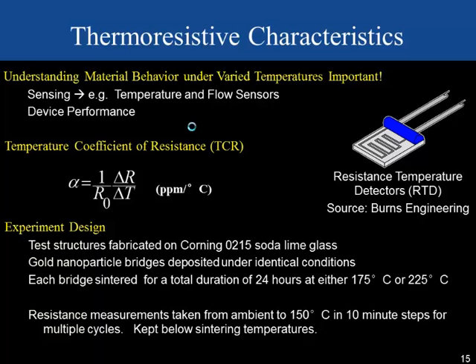For our experiment, we used the test structures outlined previously, and gold nanoparticle bridges were deposited in the same manner on all of our test structures. After deposition, each bridge underwent a different sintering temperature, either 175 or 225 C, to look at the variations. This duration was held for 24 hours to hopefully ensure that a stable gold film was rendered before the TCR measures were performed. Each sample was then placed on a hot plate setup, and the temperature was stepped through a variety of temperatures and measured to watch the response. This was kept below 150 C as a maximum, which is below the sintering temperature, to minimize effects from that.